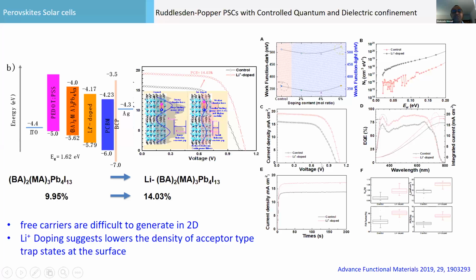So what we adopted is butylamine, which we doped with lithium. A pure layered perovskite gives you 9.95%. With doping, we were able to minimize the quantum well, and we saw a jump in efficiency. In pure perovskite, the free carriers are difficult to generate, and by doping we can lower the density of acceptor-type trap states, and then the charges can go higher. So you can follow this one here.